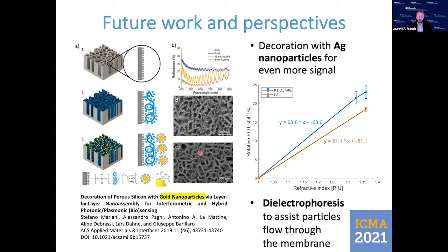As you can expect, the flow through the membrane is limited by the pore size and cannot be as high as expected. And one idea is to make a flow through in one direction and then back and forth in order to kind of trap the material inside the porous material and thus to reduce the limit of detection.